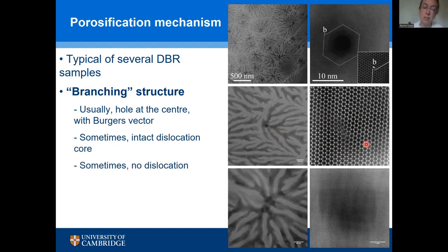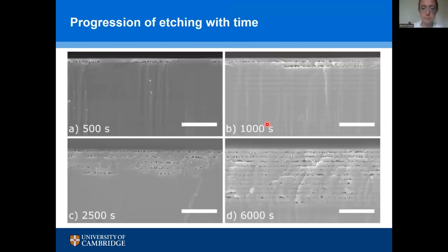I have to be honest and say sometimes we find a load of holes and we can't find the defect. And in that case, we don't know what's going on. But the vast majority of the porosity is coming from these defects, which become little tiny nano pipelines through our crystal and let the etchant access the doped layers.